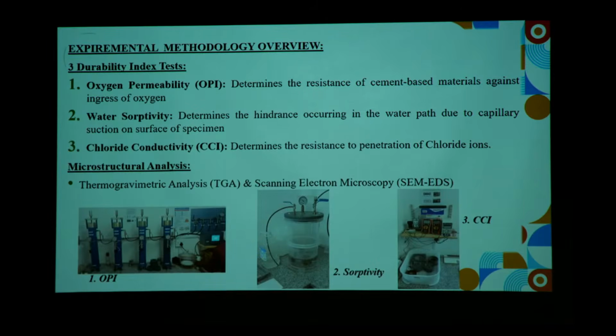So now, to get down to the durability itself, the indices that we used were firstly the oxygen permeability, which determines the resistance of cement-based materials to repel or resist the ingress of oxygen within our concrete samples. Secondly, we look at water sorptivity, which determines the hindrance occurring within that water path due to the capillary suction of the surface of the specimen. And then lastly, the chloride conductivity, which determines the resistance to penetrating chloride ions within our concrete mixture. And then the microstructural analysis would be done to validate our results. Those analyses include the TGA and the SEM analysis.